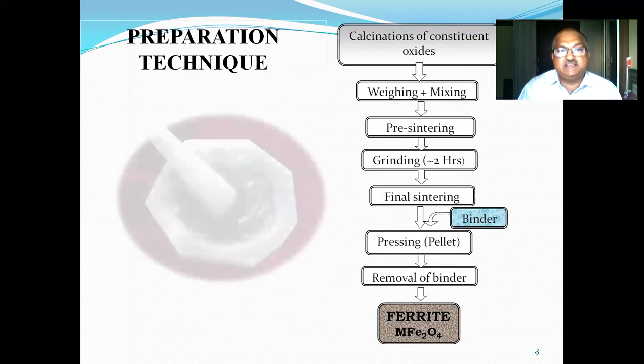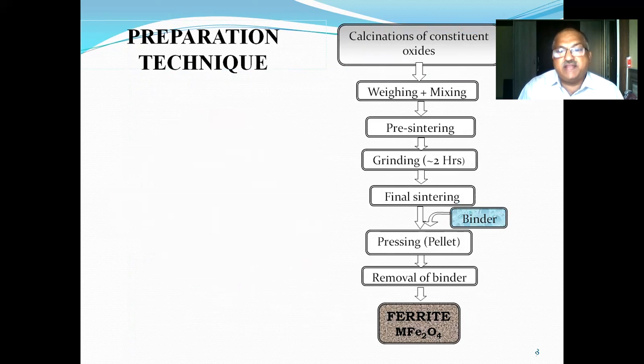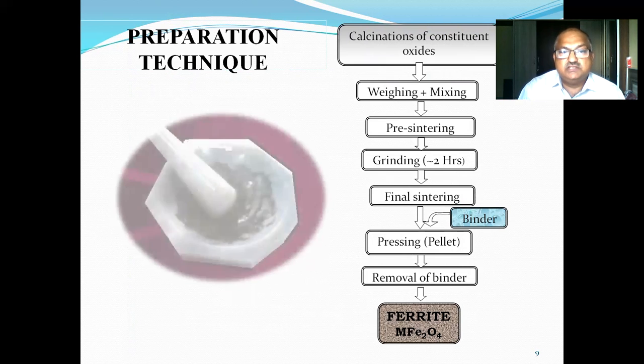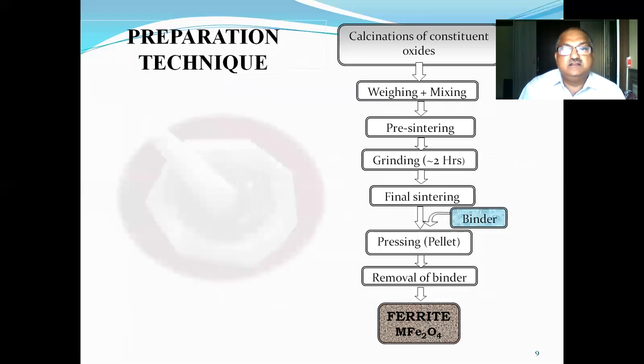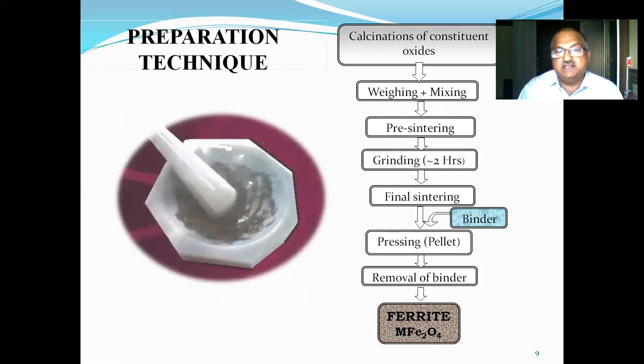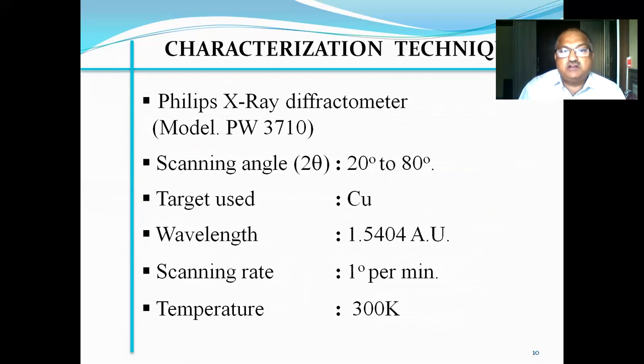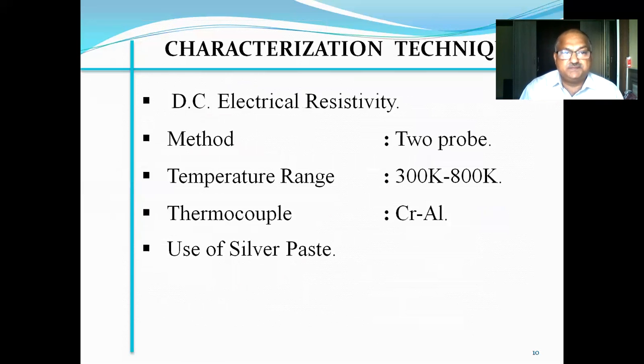This is a simple technique to prepare the ferrite material. I used the solid state reaction method to prepare the nickel ferrite material. For characterization, I have taken XRD using model PW3710. Scanning angle is 20 degrees to 80 degrees. Target is copper, wavelength is 1.5404 angstrom, scanning rate is 1 degree per minute, and temperature is room temperature. DC electrical characterization takes place by using the two probe technique, using chromel alumel thermocouples.